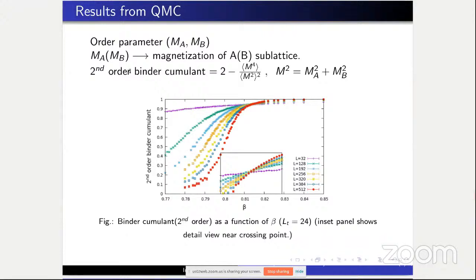Now we have calculated the two component order parameter MA, MB, where MA or MB are the magnetization of A or B sublattices, and we have defined a second order Binder cumulant corresponding to this order parameter like this, where M square equals MA square plus MB square. And this is the second order Binder cumulant versus beta graph, and here is a crossing among these curves, which has been shown in this inset panel.